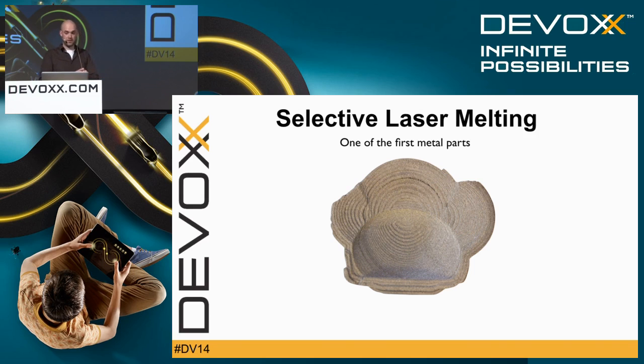This is the first metal part that I have built at KU Leuven. You can see that the quality is quite bad because you can really see the layer thickness. This was about 500 micrometers layer thickness. Now we can go up to 30 micrometers layer thickness, meaning we get better quality products.